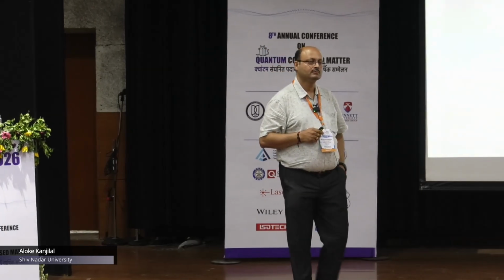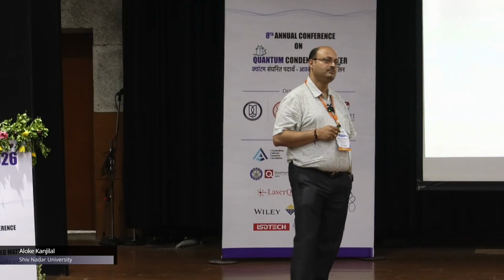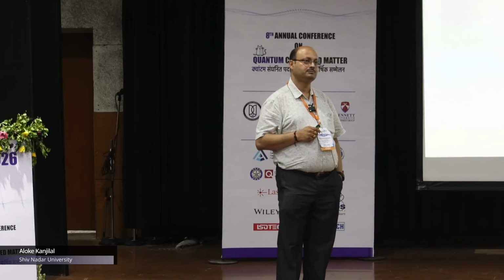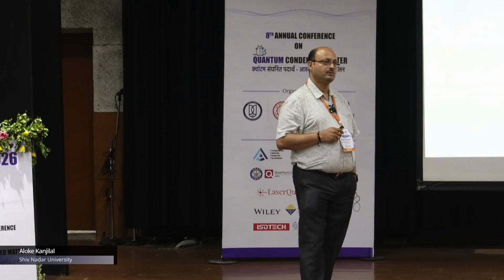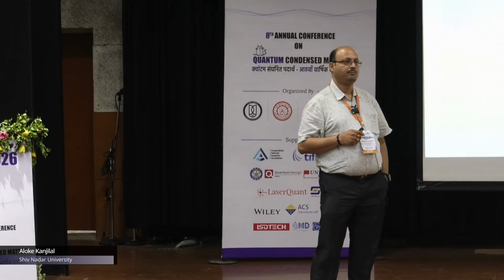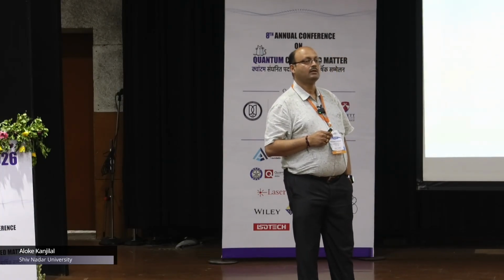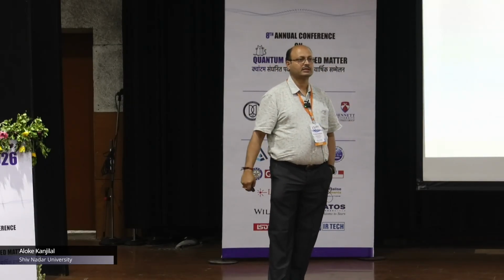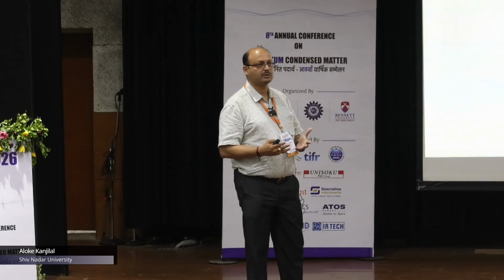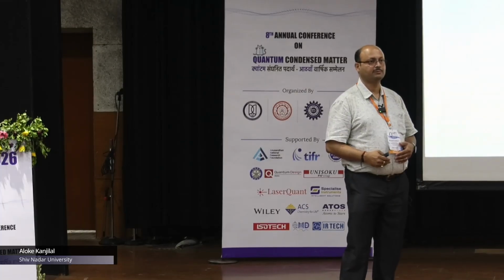Another reason can be that the atomic conductance of gold is 1 G0, but the atomic conductance of platinum, for example, is 1.5 G0. So it is possible that because of the hBN or the hafnium oxide, their combination is not 1 G0. It can be more than 1 G0. Now we are taking help of DFT calculation, so transmission channels can be calculated. For now it's an experimental observation and I'm explaining based on that. Theoretically, whenever we get some data, I can give a better explanation.